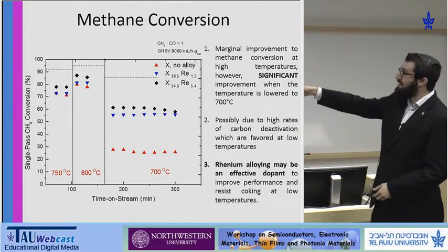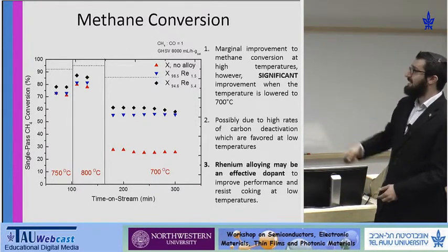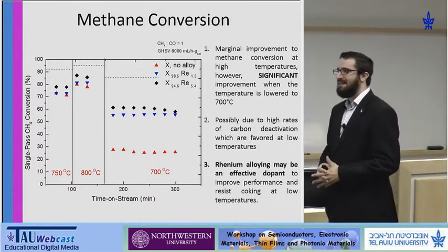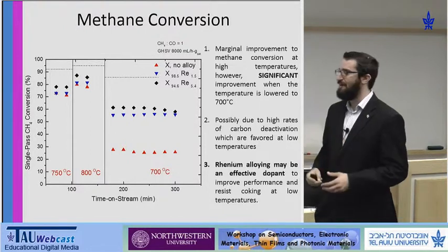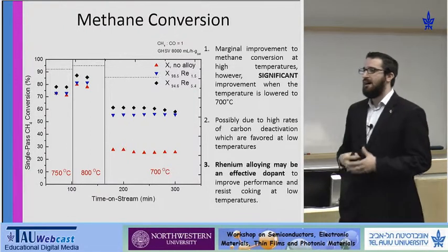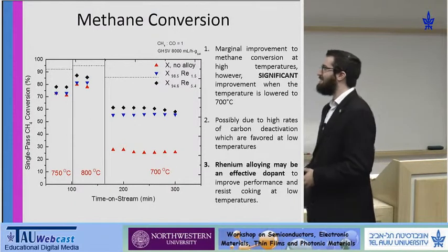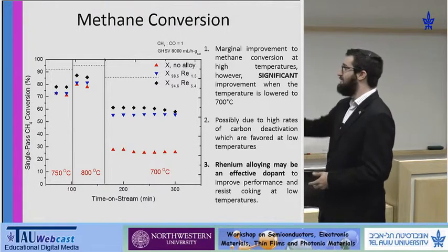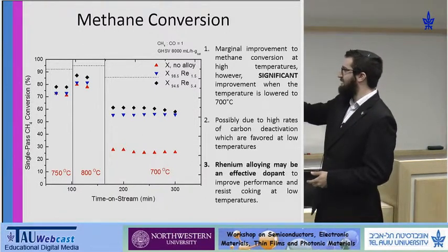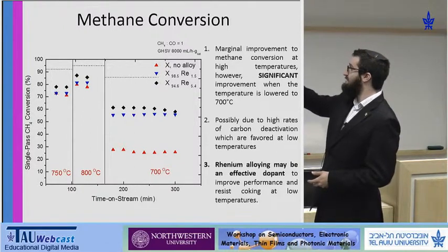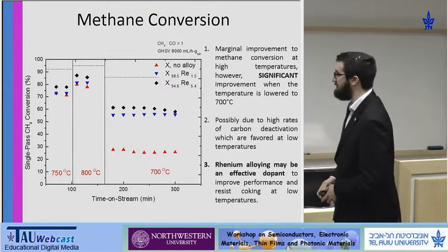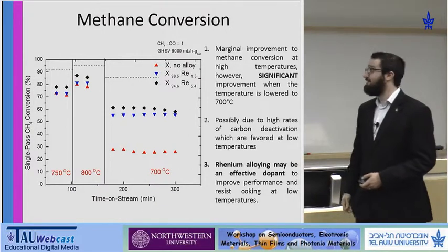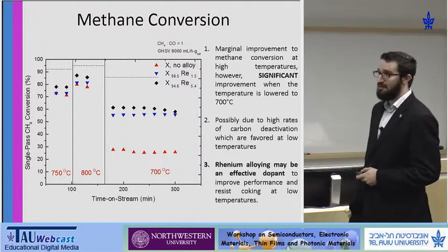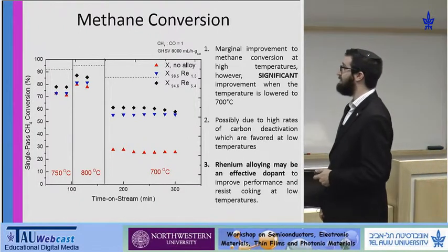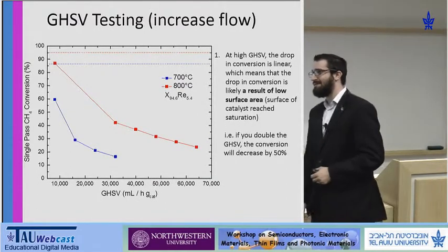And what this tells me, since over here it's only marginal, and at 700 degrees the gap is much wider, this means that there is coke inhibition forming on the surface, because at 700 degrees C, coke formation is more thermodynamically favored. And because it's more thermodynamically favored at lower temperatures, we'd expect to see this sort of catalyst death from the red triangles that we see in the unalloyed catalyst. But in the alloyed catalyst, when we drop to 700 C, we don't see nearly as much of a drop. And this could be indicative of the fact that rhenium is an effective doping material to imbue coke resistance in methane dry reforming.